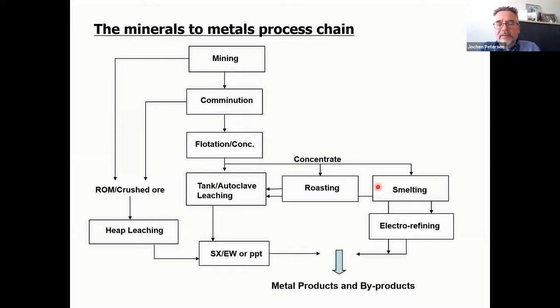And then with smelting, the classic pyrometallurgical route, you actually melt down the mineral completely and effect a phase separation, with or without reduction, between the material that you want, the melt, and the slag that you don't want. In some cases, you are making a secondary product referred to as a matte, which is then sent into a tank or, more commonly, autoclave leaching for further dissolution. Or you have the direct metal product, which may in certain cases, particularly copper, go through further refining steps such as electro-refining, or go directly to form your metal products and byproducts.